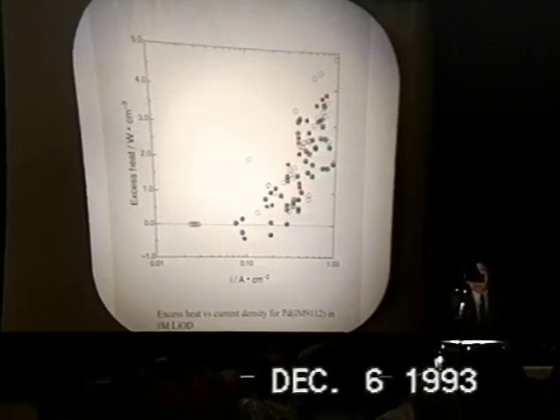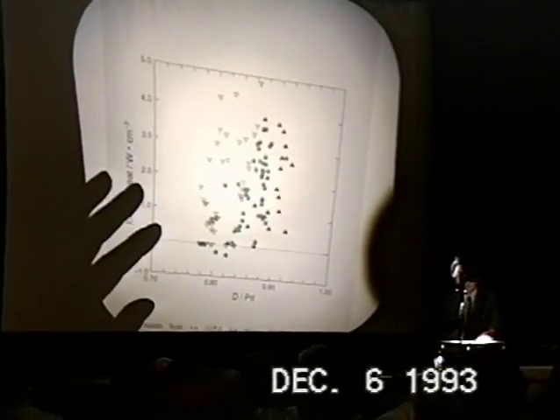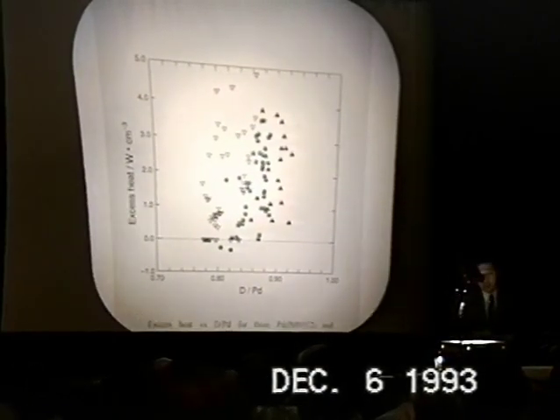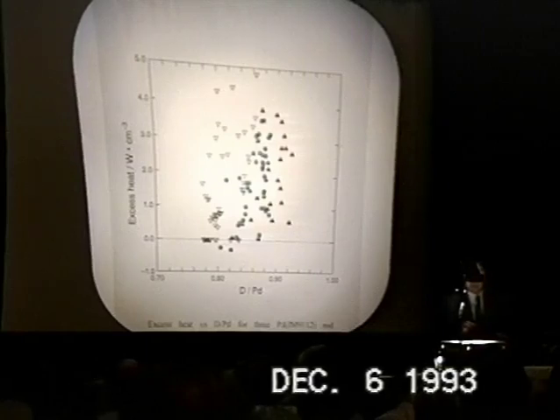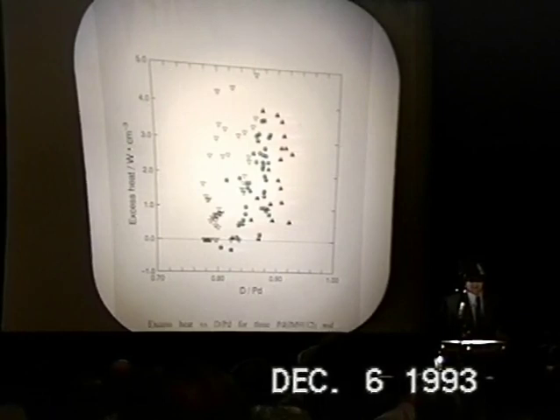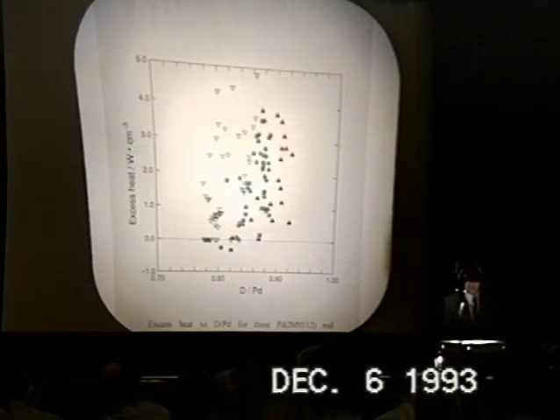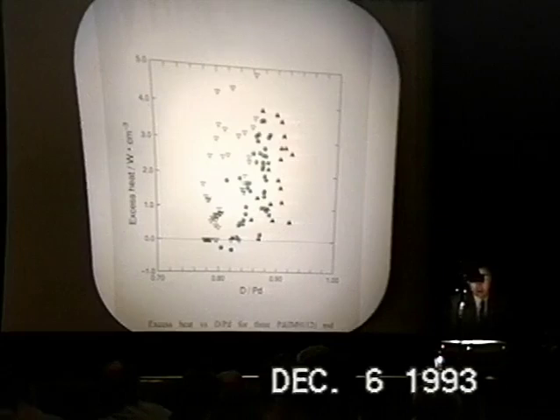The reason probably is that at that time, when we obtained this data, we were using an electrolysis cell with a very thick Teflon helix in the cell. So the Teflon absorbs a lot of deuterium gas, and this gave us a very serious problem in the accuracy of estimating the deuterium loading ratio.